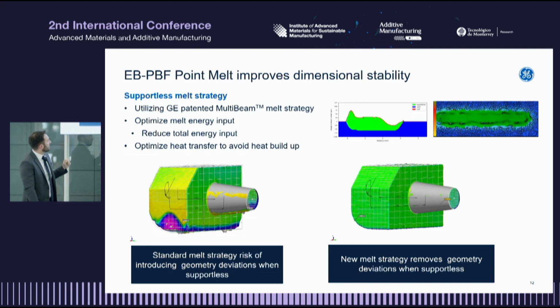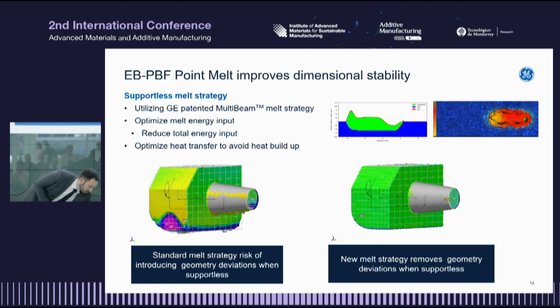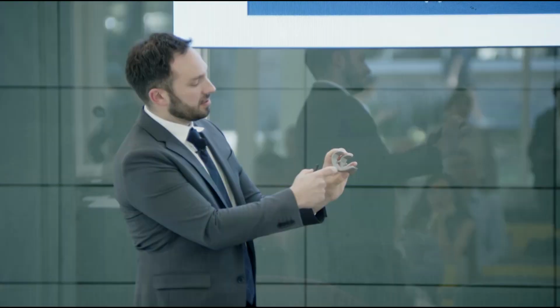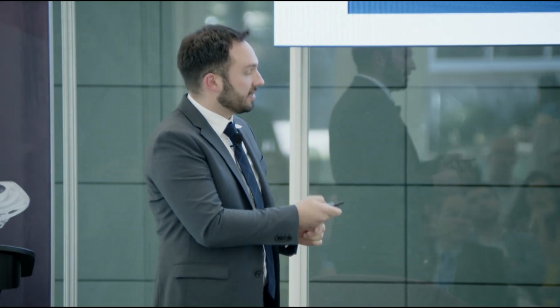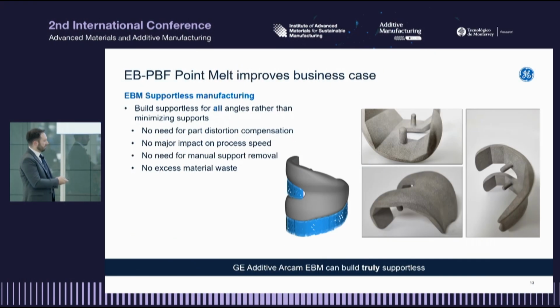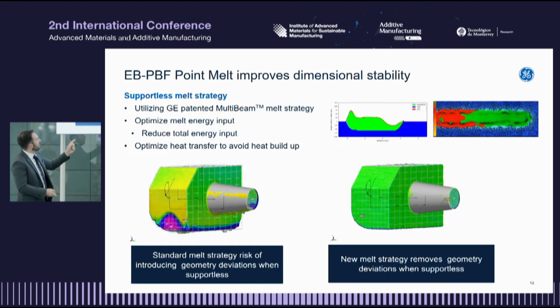On the left-hand side is, call it, a fiducial. It's made to match this location of the knee implant that I'm holding. And so the point melt on the right-hand side shows a whole lot of green and unfortunately no scale bar. But the comparison on the left-hand side is to the one that was created with classic line melting with no supports. So both supportless, line melt on the left, point melt on the right.